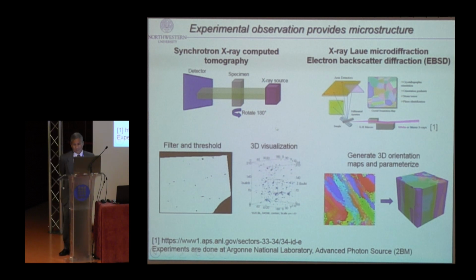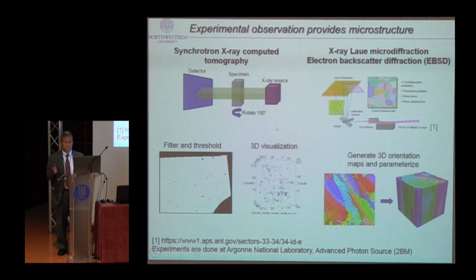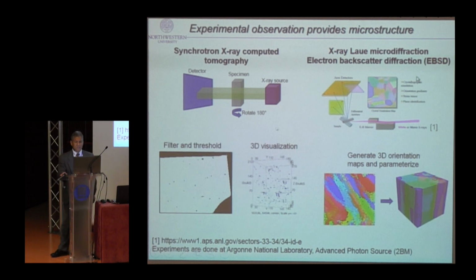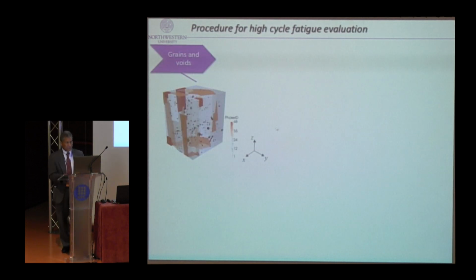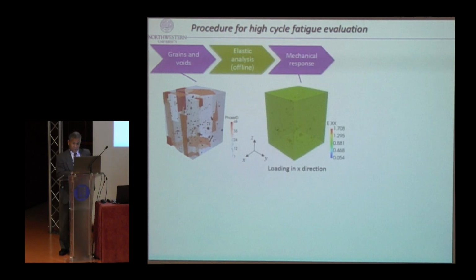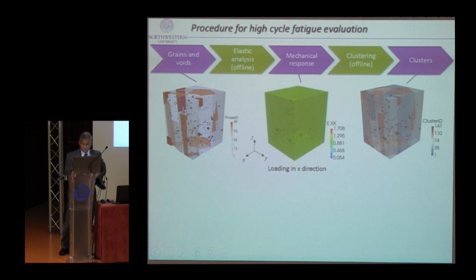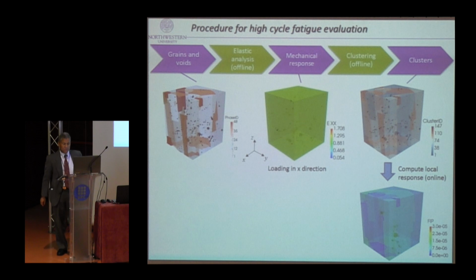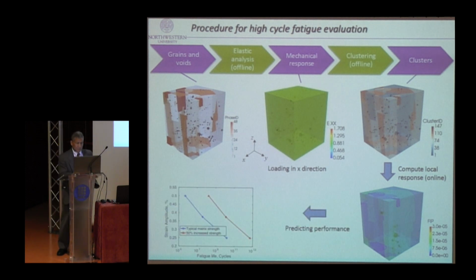So there is a lot of experimental data that we need to create from different processes in this case. And then we look at, using this technique, EBSD, the grain orientation. To do this is not trivial, from 2 dimensions to 3 dimensions. So you make a lot of assumptions on it. And from there, you can put it together, the grain structure and the voids, and you do an offline calculation. You can do elastic or plastic analysis, data compression. You can do clustering, and then now you use the Lippmann-Schwinger equation to do online predictions. And now you predict the fatigue life, and you design your microstructure.